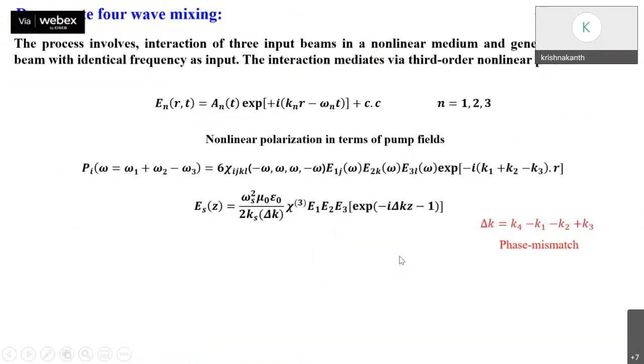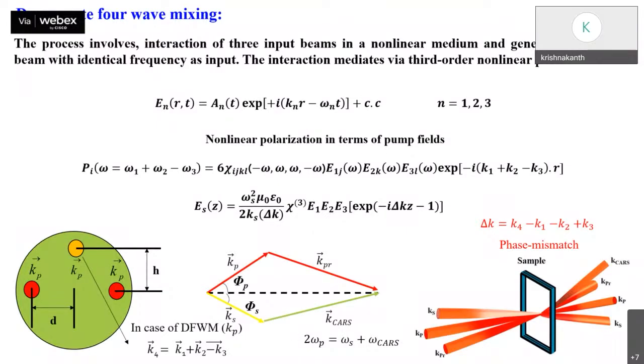This is the experimental setup, where we have a 50 femtosecond, 1 kHz, 800 nanometer system, and we have an OPA. We scan the sample along the laser beam using a translation stage, and you collect the output using a photodiode. The motion is controlled by an ESP motion controller from Newport. We also set up degenerate four-wave mixing, where you take the Libra output and OPA. As the name suggests, in degenerate four-wave mixing all the beams have the same frequency. The three beams were aligned in a boxcar geometry, as shown in the corner. This is our degenerate four-wave mixing signal, the fourth beam, collected in a lock-in amplifier, and we also get the response and magnitude of chi3 here.